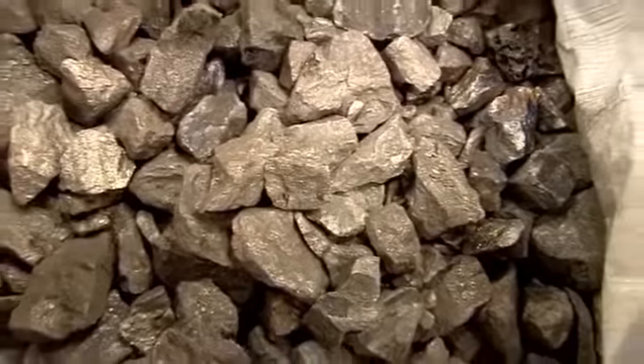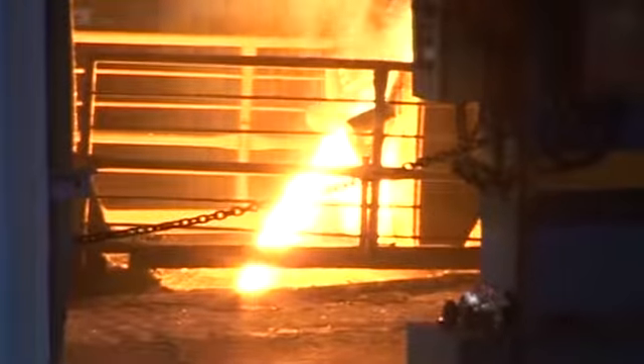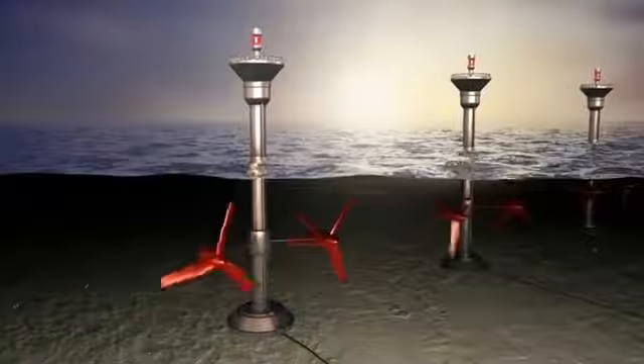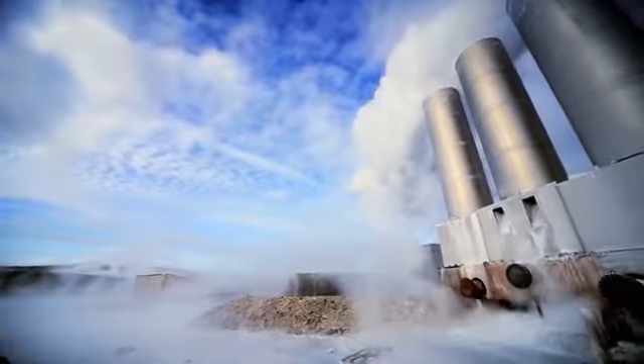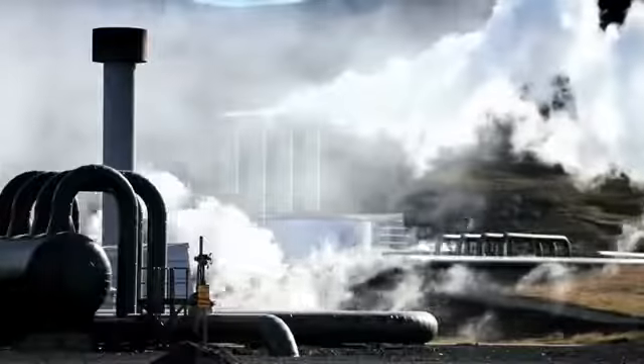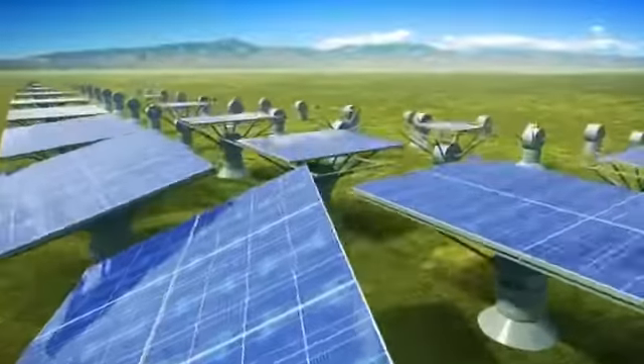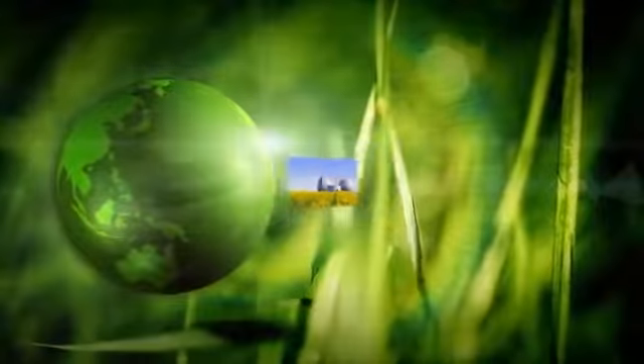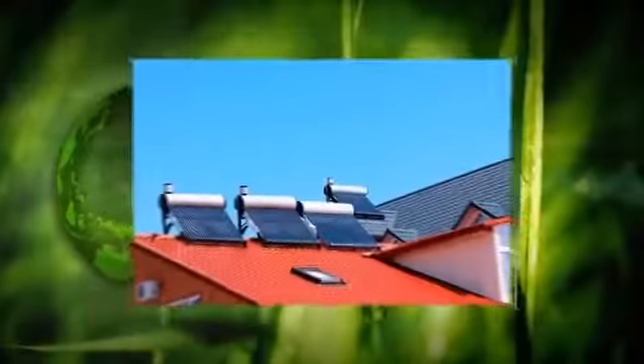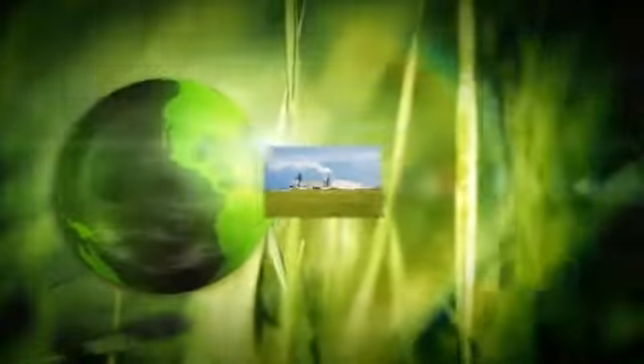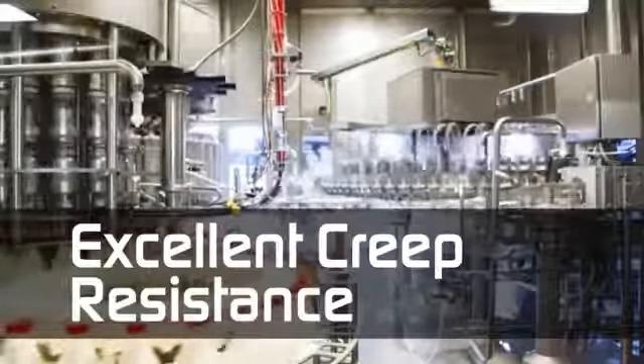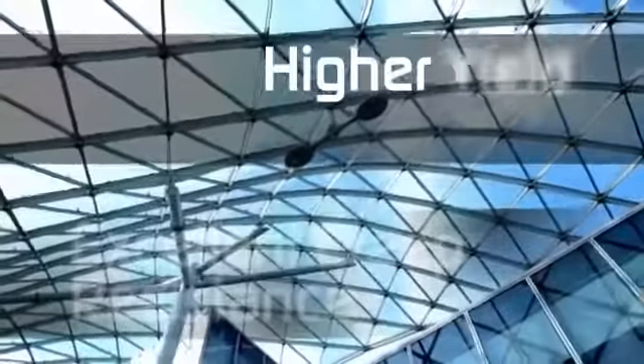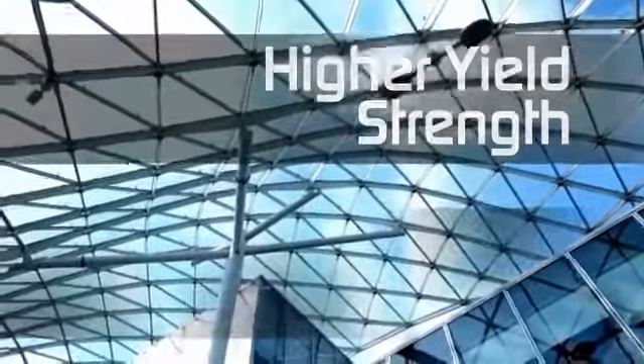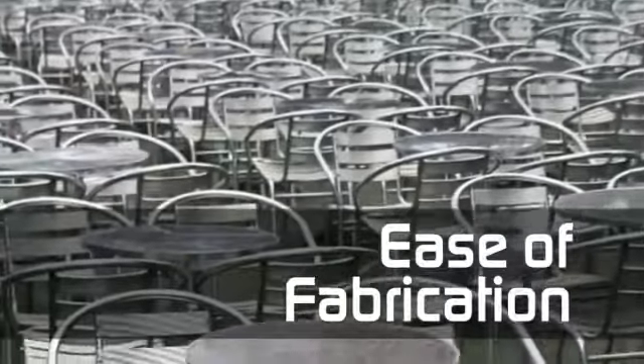There is no doubt that the next few decades will witness further remarkable refinements in the use of niobium in stainless steels, and that such developments will make a significant contribution to our more effective utilization of the world's resources. Ferritic stainless steels offer a more sustainable and lower-cost alternative to austenitic steels in a wide range of applications. Reducing nickel to either 0 or just a few percent, and microalloying with very small additions of niobium and molybdenum in a ferritic matrix has been demonstrated to produce stainless steels with properties equivalent to those of many austenitics in terms of corrosion resistance, toughness and formability.